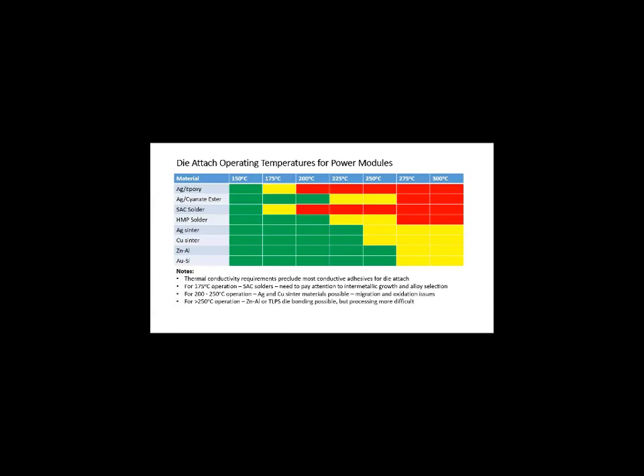For silver and copper sinter materials, I think there are very attractive areas there, but certainly on the silver side, you've got to be very careful about migration, and on the copper side, you've really got to be careful about oxidation and how you protect the copper from oxidation. Going towards 250 degrees C operation, you're getting into more exotic die attach or substrate attach materials such as zinc aluminium and transient liquid phase soldering, which I'll come on to.